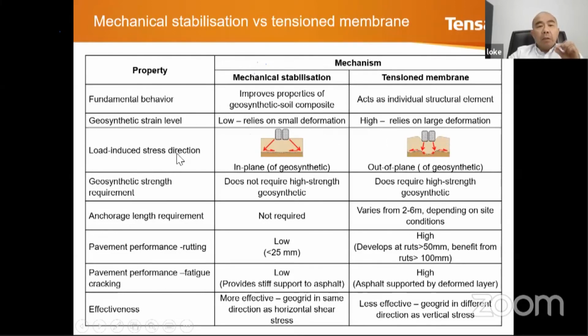Okay, the load-induced stress direction is in the plane, and this is out of the plane. Geosynthetic strength requirement, it does not require a high strength geosynthetic. This requires a very high strength geosynthetic. Anchorage length requirement, it does not require anchorage length at all. You don't need to anchor it. Here you need to. If you don't anchor it, then the whole thing will zoom inside the soft ground. Pavement performance rutting, normally very low. And you can see test and test over and over again, even with asphalt, it is less than 25 millimeters. Mostly the rut depth will be very high, more than 50 millimeters. The whole thing will just crack.